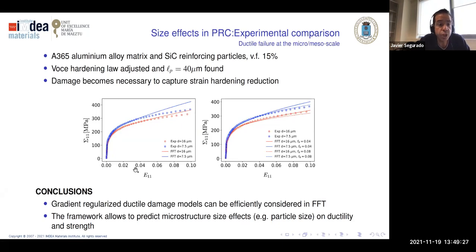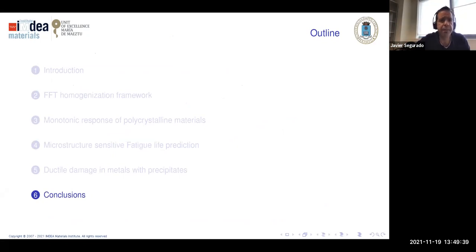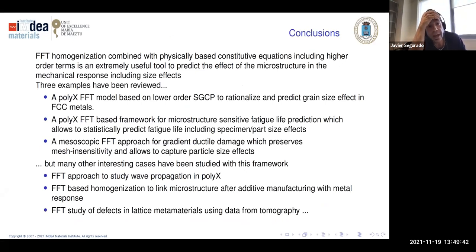Okay, so this is the conclusion. You can use gradient models quite efficiently in this framework, and we can further extend this to crystal plasticity. So I have more or less finished on time. Let me just recall what I have told in this webinar. What I have tried to show is that FFT homogenization, if combined with physically clever constitutive equations, and these equations might be complex, like strain gradient plasticity, or coupled PDEs, like in the gradient ductile damage model, but if we use the correct physics and the correct mechanics, we have an extremely useful tool to predict the effect of microstructure on the mechanical response.